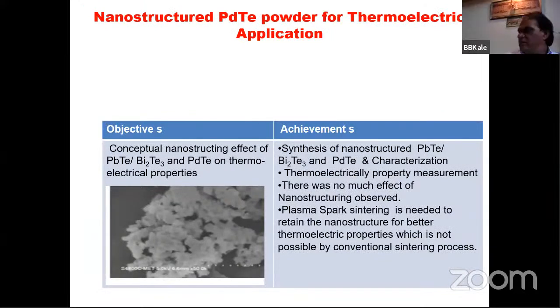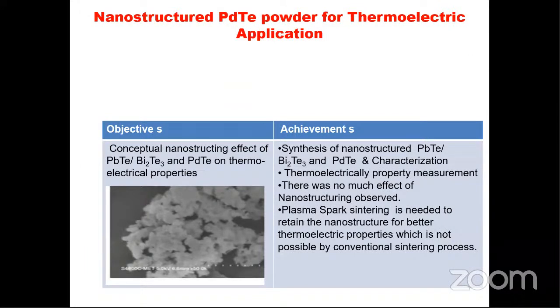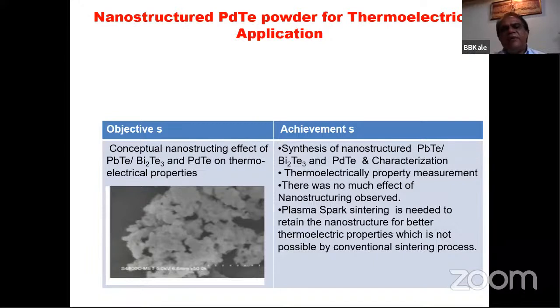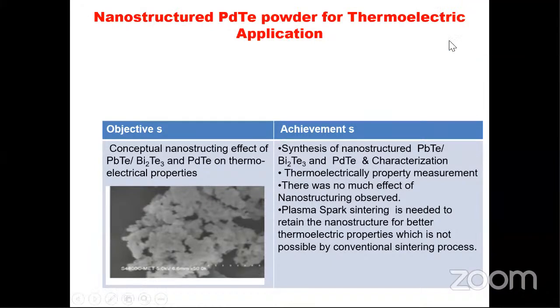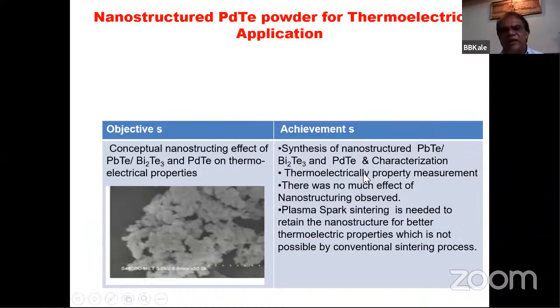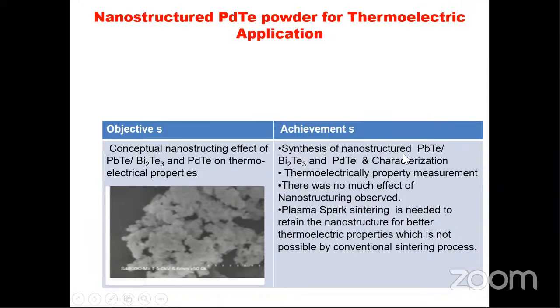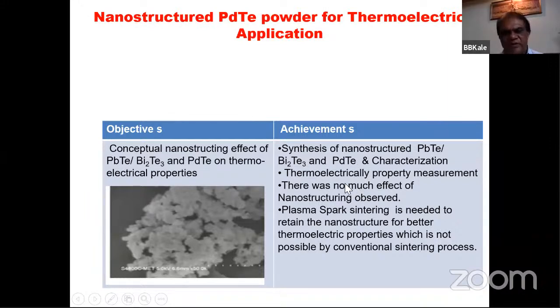Then thermoelectric material. Thermoelectric material, I will explain to you. One is the Peltier effect and another is the Seebeck effect. For this Peltier effect, this lead telluride is a good material. We can get ZT around 1.2, something like that, and we can use it for cooling devices. So we just made a powder now, lead telluride. Lead telluride and palladium telluride, not much difference, but lead is banned, so we are talking about palladium, so it's costly. So we made around 20 to 30 nanometer powders, and now we are making PN junctions and making devices.